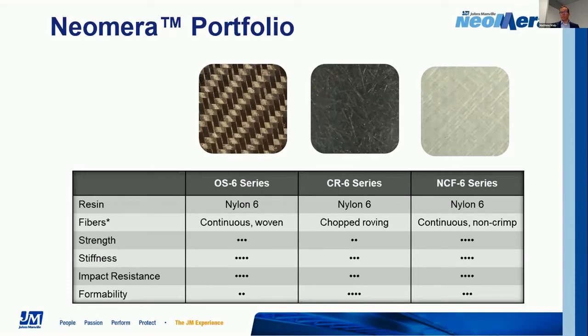And then the third series is our CR series, our chopped roving series. And this one's really interesting in the sense that it has all the benefits that the AP nylon system provides, but it also has a reinforcement similar to what you would see in an SMC process, but it's a thermoplastic. So, it's roughly 1 inch long fibers oriented sort of randomly. So you get quasi isotropic properties from it. And this material really comes into its own in applications when you need a lot of formability. As you heat these materials up, those fibers are really allowed to move and to flow on top of each other, which is going to allow you to produce shapes that you never were able to do with a traditional Organosheet, both because of it being a short fiber, as well as the really good wet out of the reinforcement.